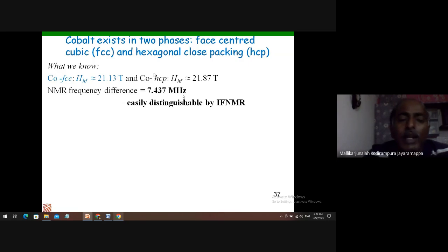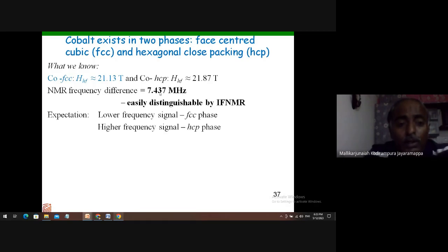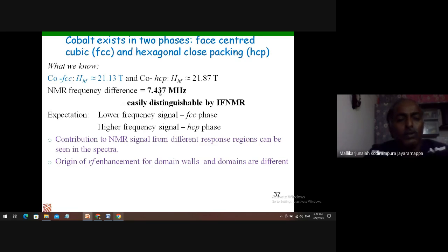If I convert this magnetic field in terms of NMR frequency, there is about a 7.4 megahertz difference between the two peaks we observe in this internal field NMR spectra. Hence, it is easily distinguishable by IFNMR. Whenever we see two signals, I can always attribute them to the FCC phase and the HCP phase. And once I know that, I can always estimate the domain wall contribution and the domain contribution.